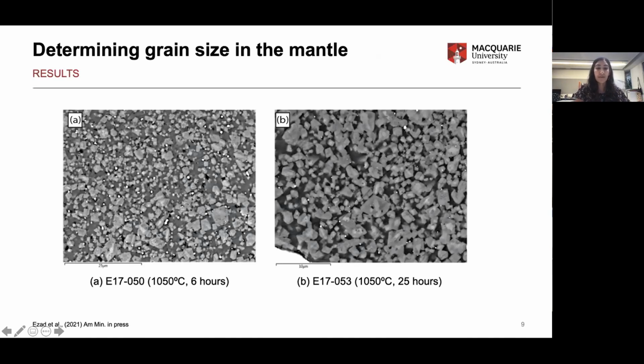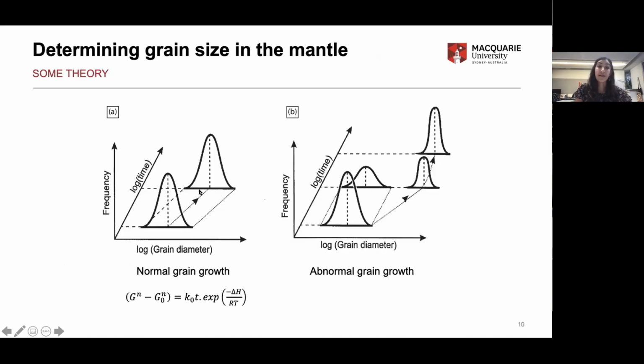It became very clear straight away that I wasn't going to be able to measure the grain size of my orthopyroxene grains because they've just gone into a matted background texture with very poorly defined grain boundaries. Luckily, because I made my mixture 50-50, I could still constrain the kinetics by measuring the grain size of the spinel grains, which leads me to grain size theory. This is the only bit of maths you'll see today.